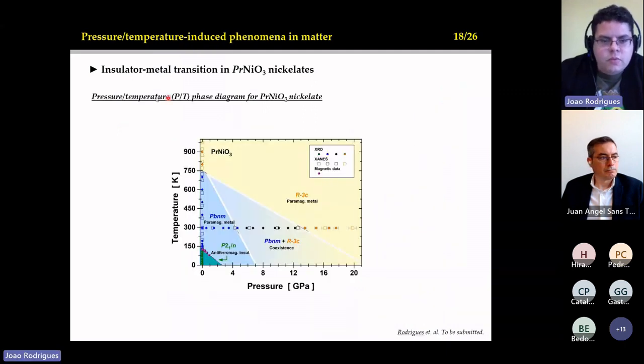And then the conclusion of the work was to provide a very nice pressure-temperature phase diagram for this material, where you have all the transitions occurring at ambient pressure, with high temperature and low temperature, and also the coexistence range here, and also the dependence of the antiferromagnetic insulator on pressure. This work is to be submitted very soon.